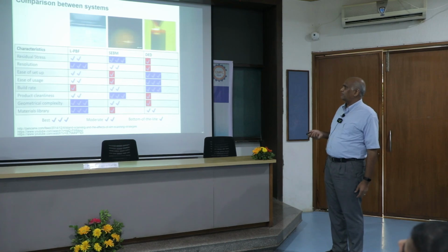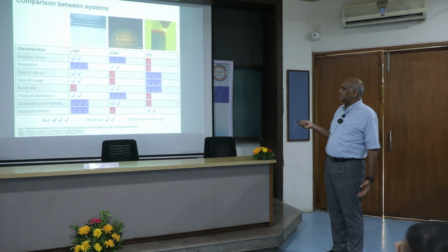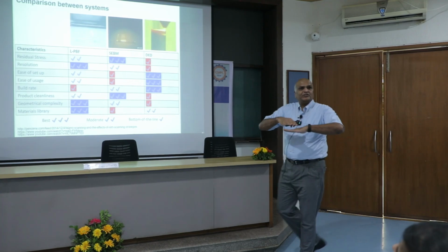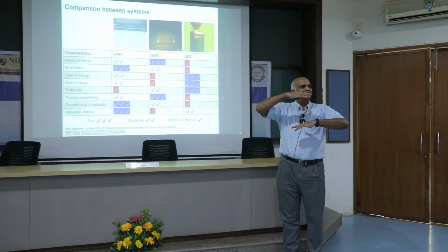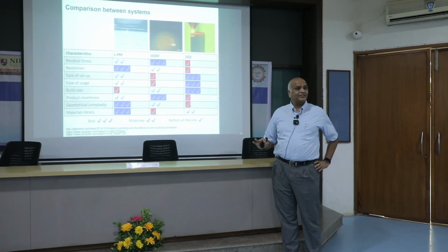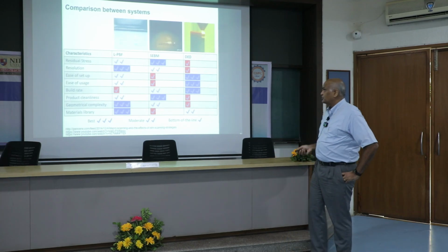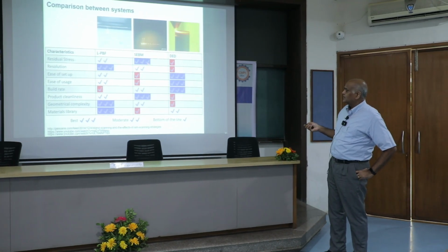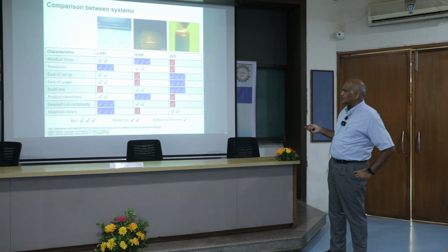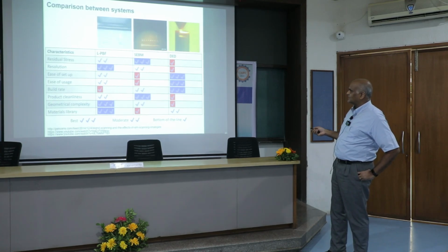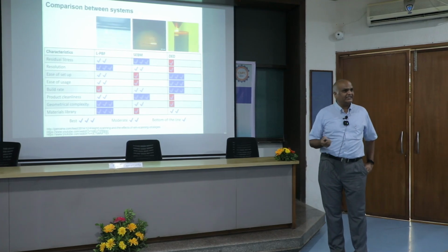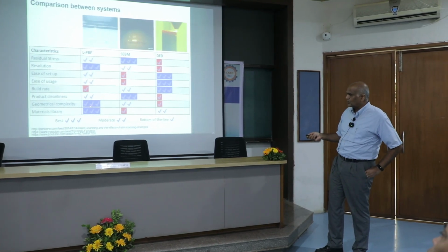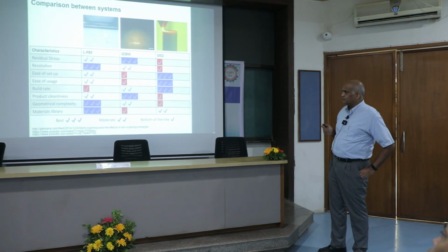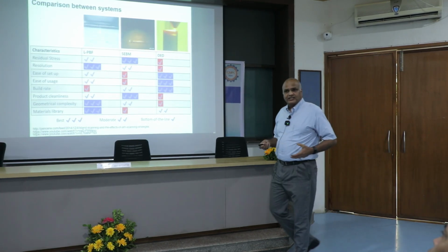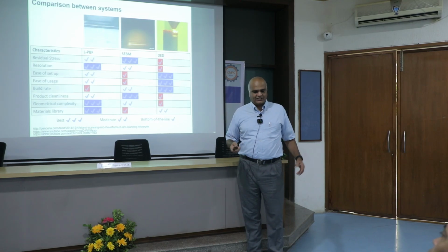So this tells you the 3 different techniques and their advantages. For example, from a residual stress point of view, because you're depositing layer after layer, there is a heat buildup. So there are significant residual stresses that build up in these things. From that perspective, the electron beam melting technique is much better. If you are looking at low cost, easy to set up, easy to use, high build rates, DED is a much better technique. And if you want very complex shapes to be built, LPBF is better. So these are the kinds of advantages and disadvantages one has in these methods.